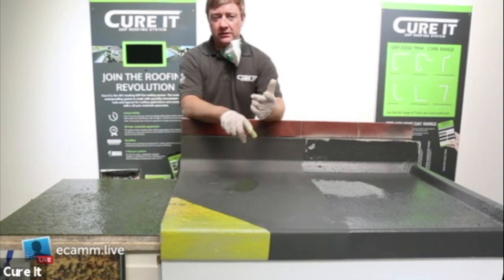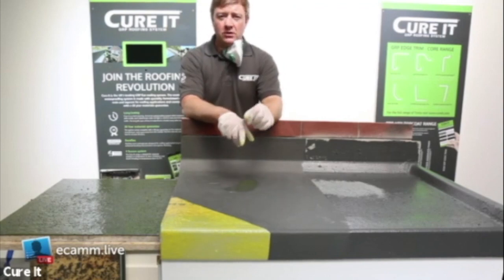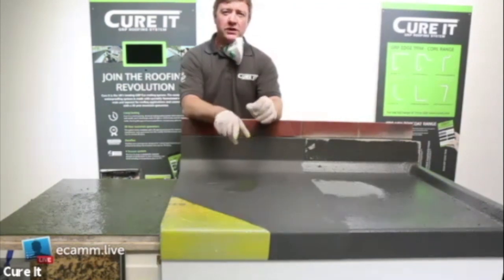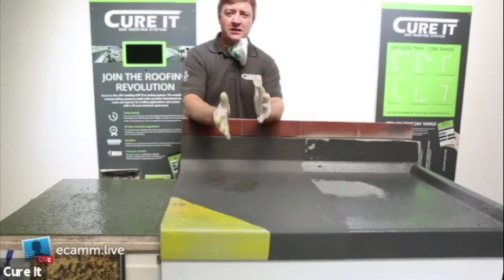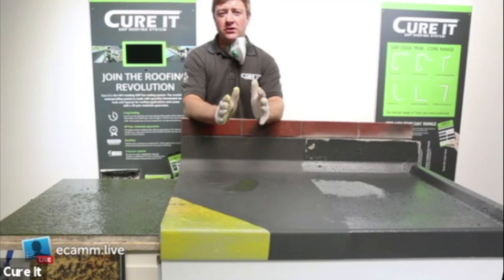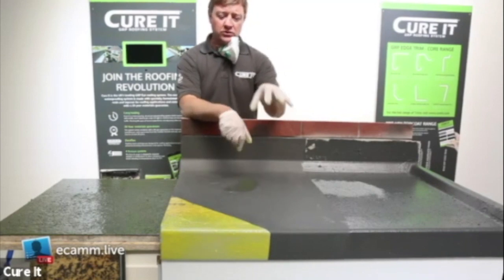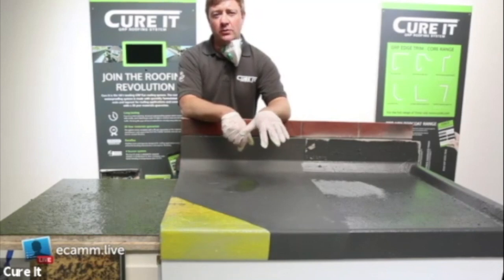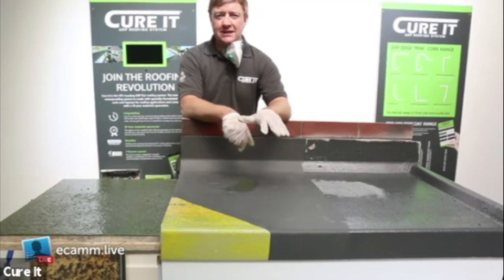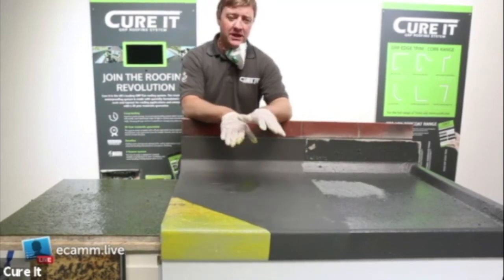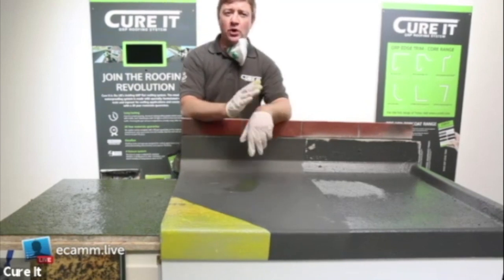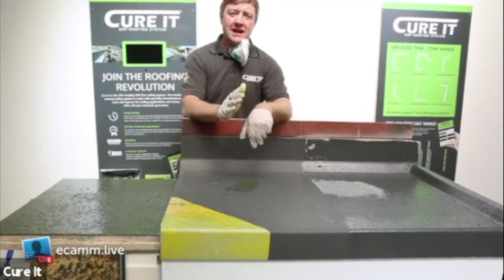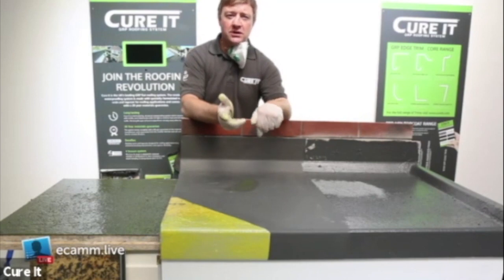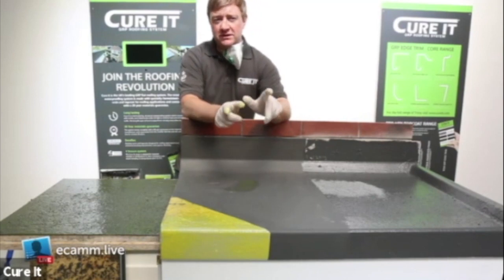But also, when you're top coating, especially in the winter months, which are coming upon us at the moment, well later on, it's roughly a 3 month period in the winter, and 3 o'clock is really a cut-off. The reason for that is it does rely on the UV sunlight for the top coat to cure. And if there's no light on it, it can cure quite patchy in places. But also it can be exposed overnight as well, so it can stay slightly tacky overnight, exposed to the elements. I've got a little picture here for you, which is contamination.